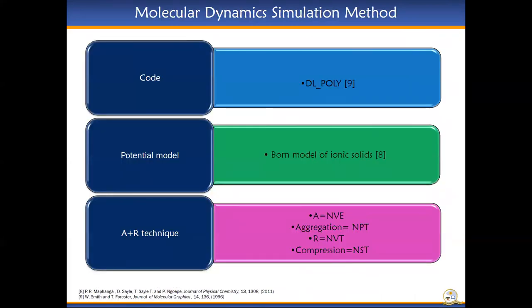Simulated amorphization and recrystallization technique based on molecular dynamics using the DL-POLY code and the Born model of ionic solids were employed to amorphize and recrystallize three Li-Mn2O4 nanoporous structures of lattice sizes 75, 69, and 67 angstroms at different lithium concentrations, where the NVE ensemble was used for amorphization, NPT for atom aggregation, NVT for recrystallization, and NST for compression.